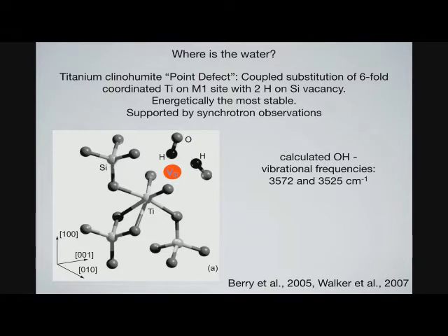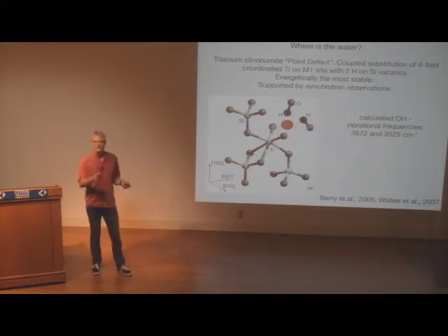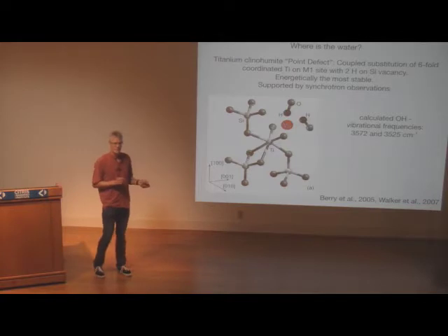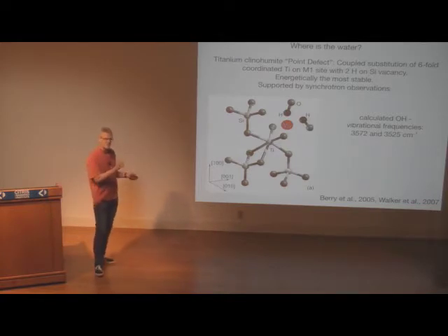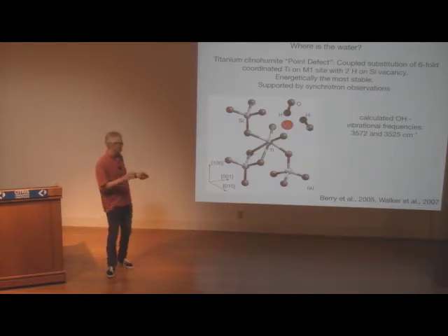What you see in the infrared is basically the vibrational energies of the hydrogen coupled to the oxygen. And the hydrogen, of course, is surrounded by the larger crystal structure. That gives rise to these particular absorption bands. So if you have these localized absorption bands, that tells you that hydrogen is incorporated in the olivine crystal structure as a defect compound.